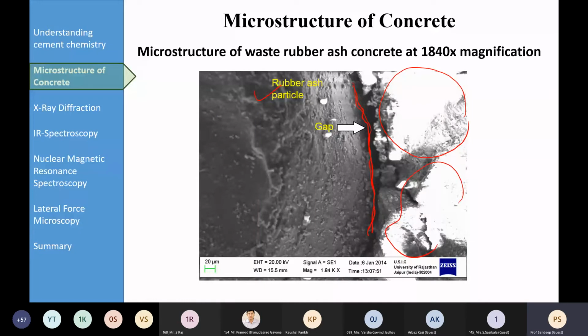this gap is basically a sort of interfacial transition zone, and that is going to cause weakness in the concrete. And that means the strength which we are going to observe for the rubber ash concrete is going to be less than the normal concrete. And this is what we found when we actually tested the concrete. But the idea is that once we did the microstructure analysis, we were quite sure that this is going to happen, and there was a sort of validation by the strength test also.